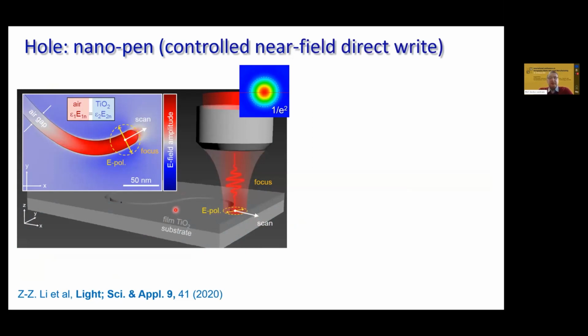Okay, and the very final thing is to show that we can use a femtosecond laser, tightly focused, almost in a way of electron beam lithography application. So here you see the titania film, 10 nanometers. Let's consider it as resist, and it's sitting on some transparent sample, let's say silica glass. Then if we have a nanogroove and we are focusing a femtosecond laser on this type of structure, the focus is larger, obviously, but if we have a very narrow groove, what happens is that light will be very happily concentrated in the air part of this illuminated region.